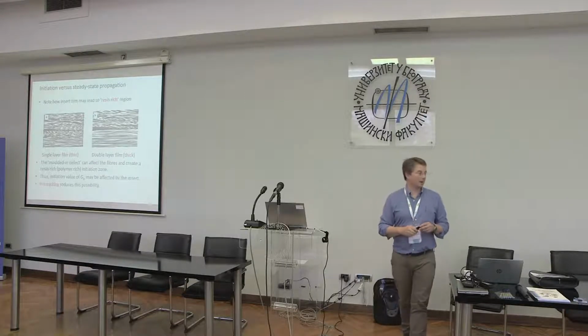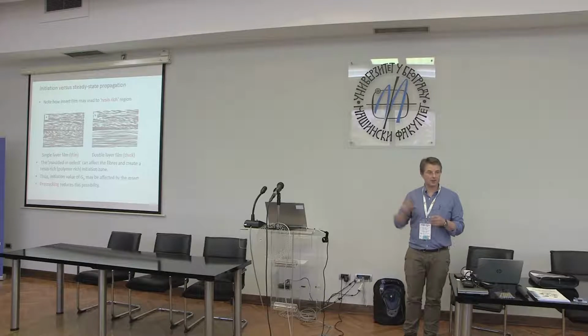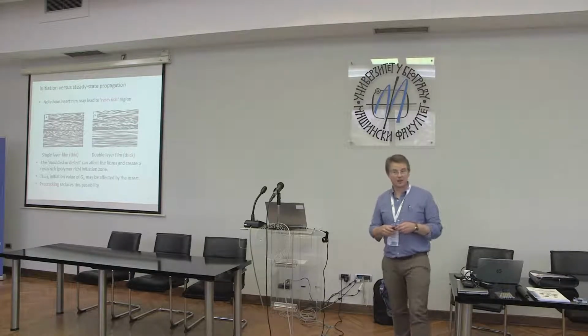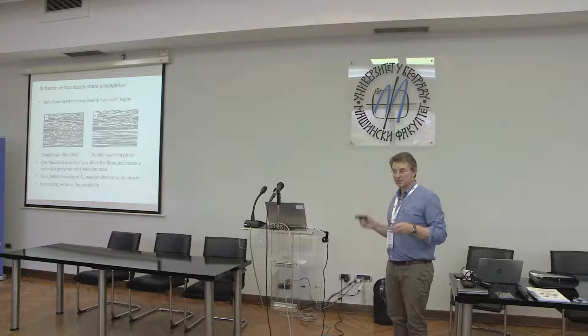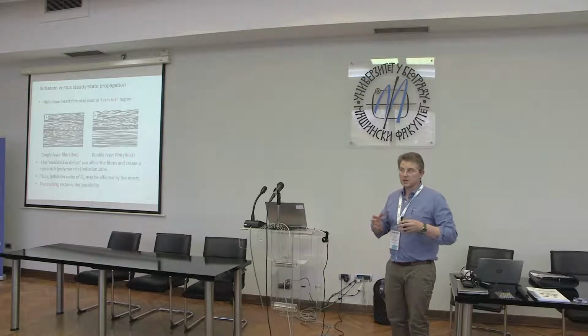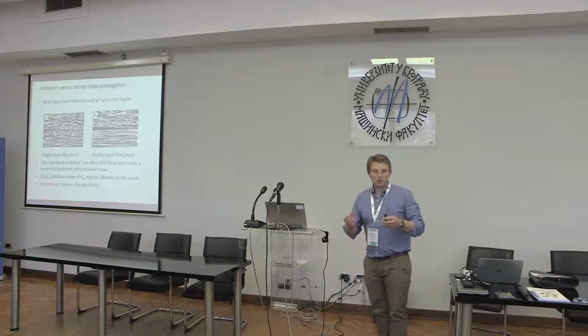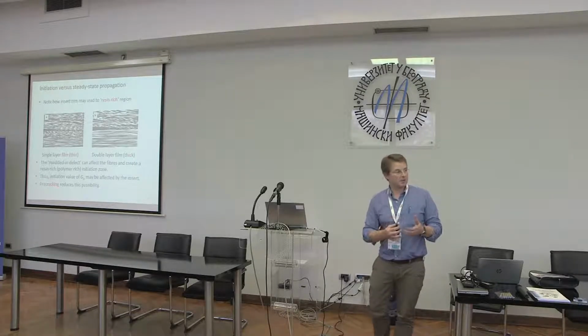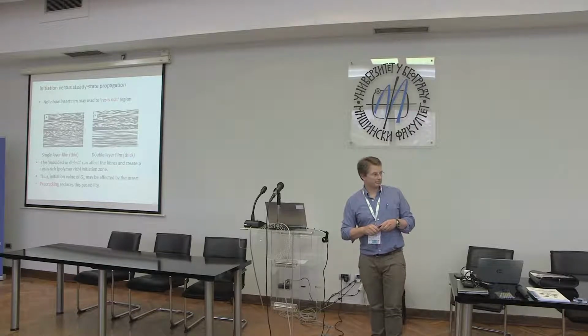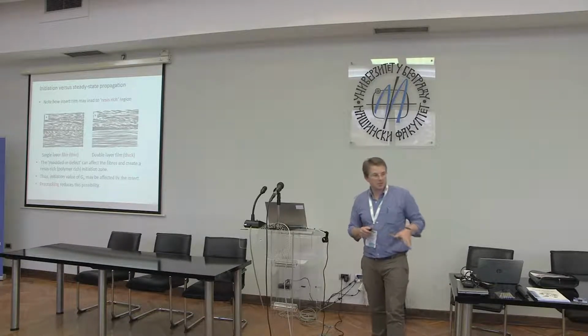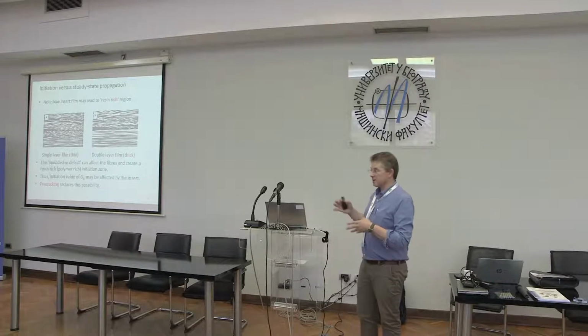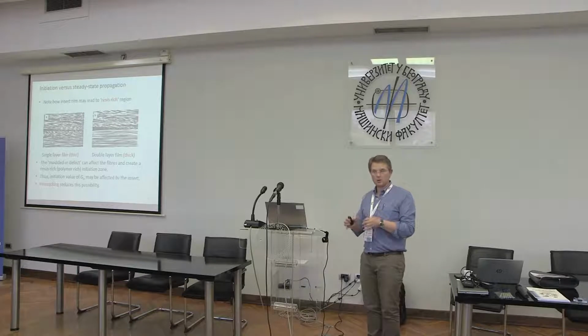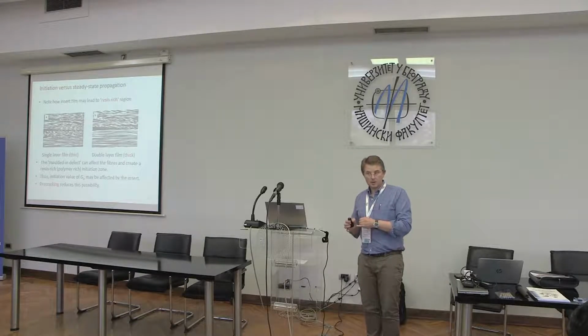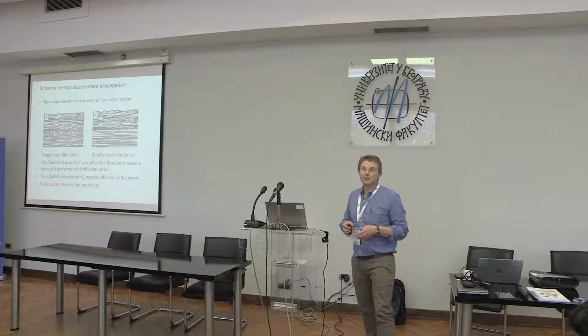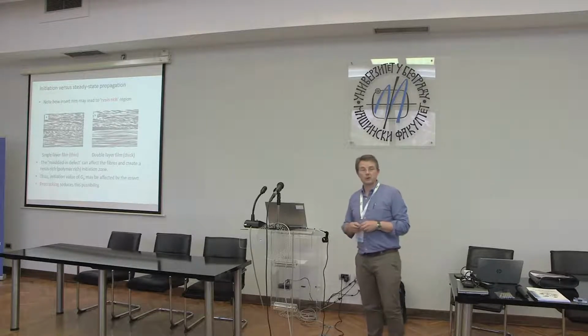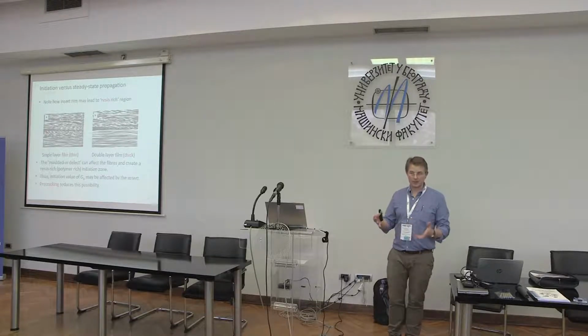Now that's true partly in as much as, of course, if we have a strong R curve, so if we have an increase in fracture resistance after crack initiation, which certainly can occur with these materials, then what you're measuring is, for example, the proportion of the extra energy being dissipated by mechanisms such as fibre bridging. And fibre bridging is somewhat specimen dependent, okay? But you have to make that distinction, and if you are interested in the initiation and the propagation value, you've got to actually have confidence in it. You've got to try and get it right.